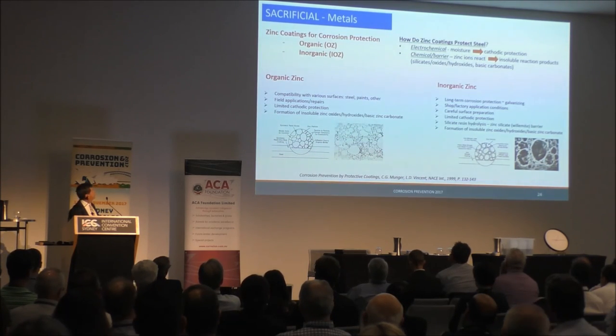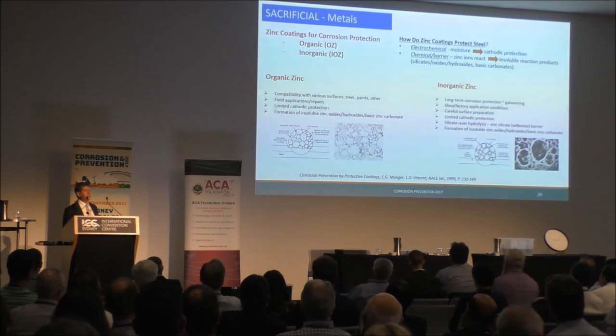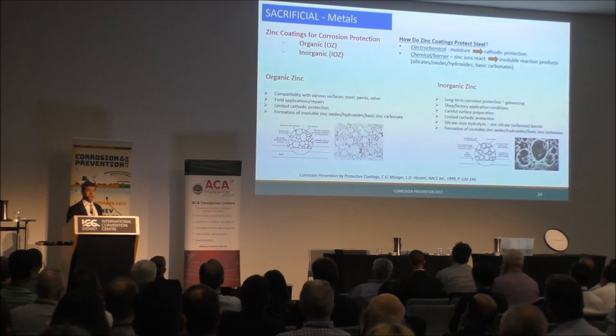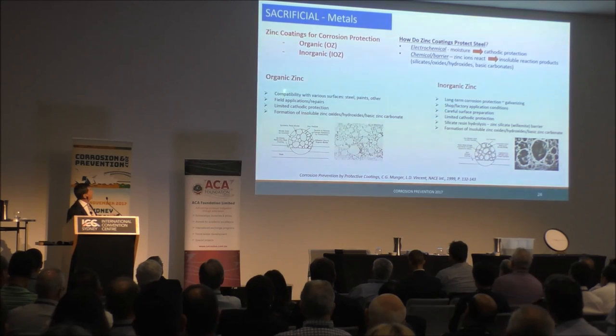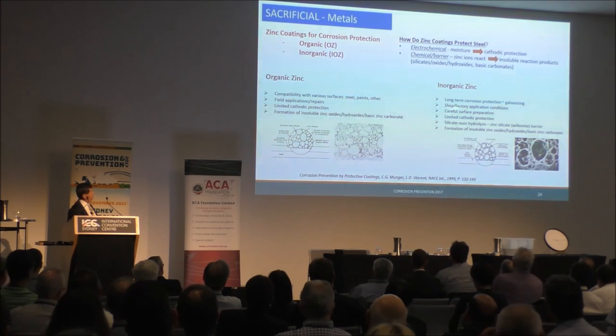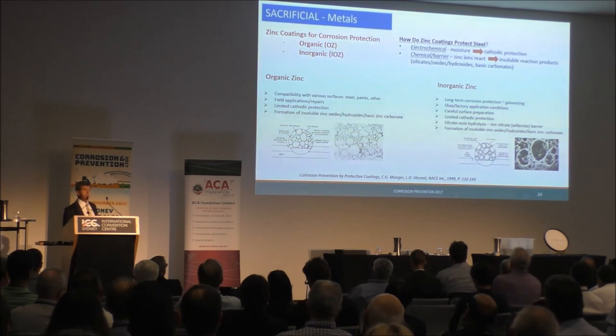I'll just mention very briefly the sacrificial zinc-rich primer systems, because these are tremendously important in terms of practical performance for engineering structures all over the world. There's at least 30 to 40 to 50 years of experience with these coatings. They function extremely well, particularly under the right conditions. There's two types. There's an organic resinous zinc-rich primer system, and there's an inorganic ethyl silicate type zinc system. Both have their advantages, both have their disadvantages. Both systems essentially function with a degree of zinc.